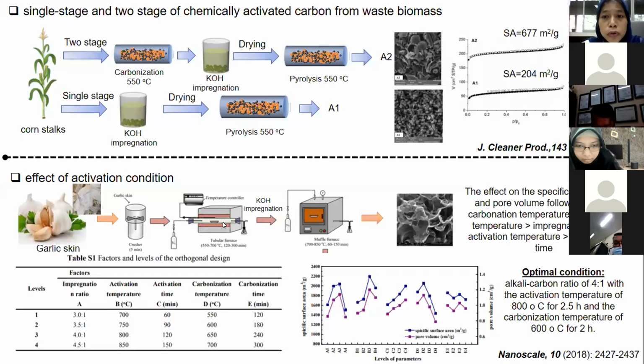Both methods produce an activated carbon with different porous character. The sample after the single stage process was more homogeneous and well structured, while the two-stage pyrolysis caused cracking of the network and creation of heterogeneous particles with a quite irregular structure, with opening of pores and structure on the surface. This phenomenon was caused by the pre-carbonization step before the chemical modification. Thus, the chemical agent can react differently with carbon char as it did in the single stage process. Activated carbon prepared by two-stage pyrolysis saw better porous development related to high porosity and surface area, and those parameters are related with much better adsorption properties compared to the single process.